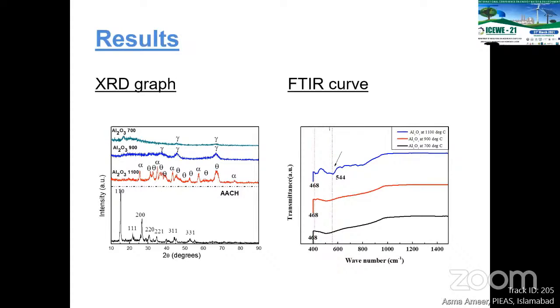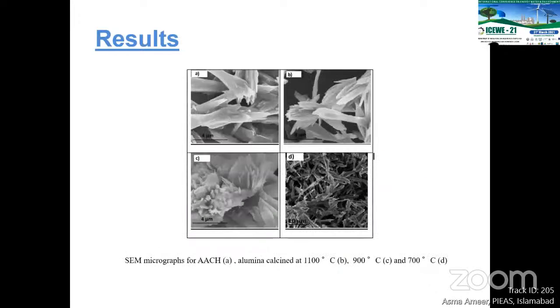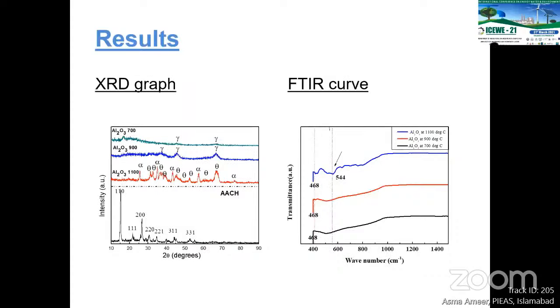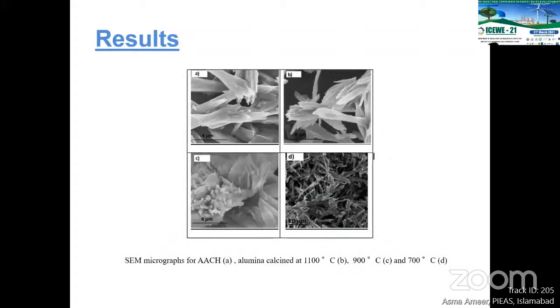Next is the FTIR curve, and in FTIR we can see that aluminum oxygen vibrational peaks are observed at 468, and for higher temperature calcined alumina, the aluminum oxygen peak occurs at 544 per centimeter wave number. These are the scanning electron microscope micrographs, and these SEM images are showing the whisker-like morphology. The advantage of whisker-like morphology is that it has greater aspect ratio and higher surface area, which help in the adsorption process.